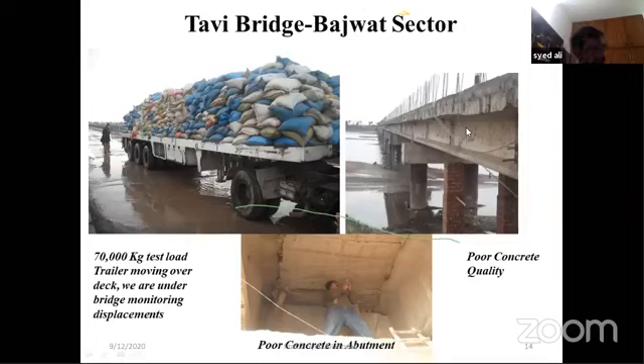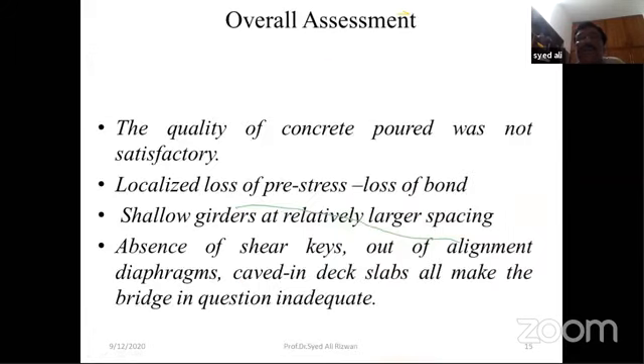When we examined the lateral reinforcements connecting the bridge decks, they were also found not up to the mark. The overall assessment you can sum up in these words. The quality of concrete poured was not satisfactory. You should remember that in pre-stressed concrete, FC prime should not be less than 5 KSI or 5,000 PSI. Then localized loss of pre-stress was also visible because there was loss of bond between concrete and the pre-stress reinforcement.